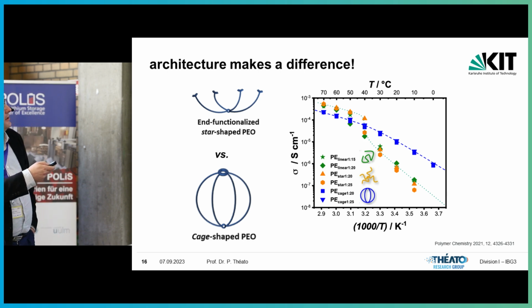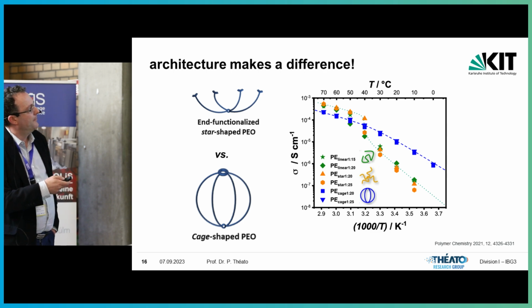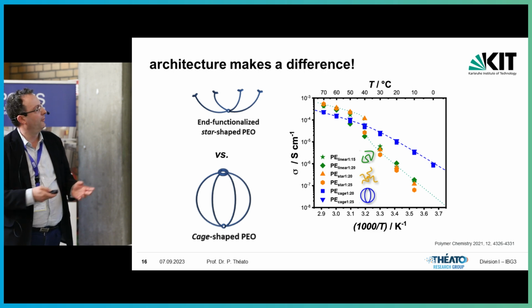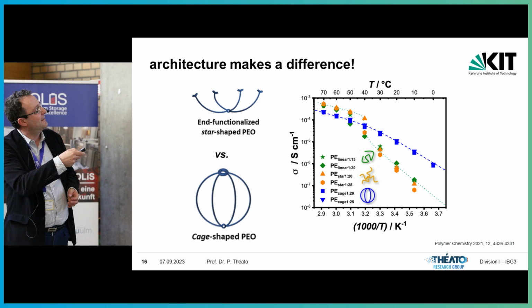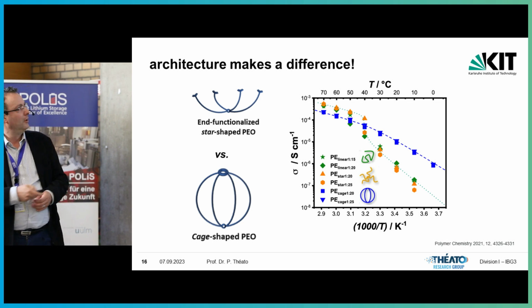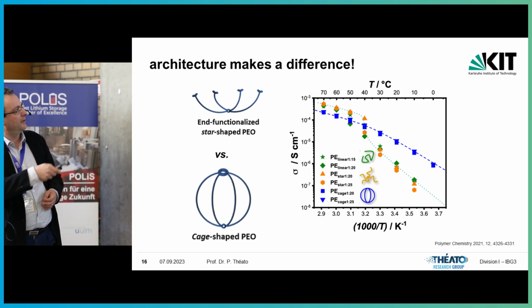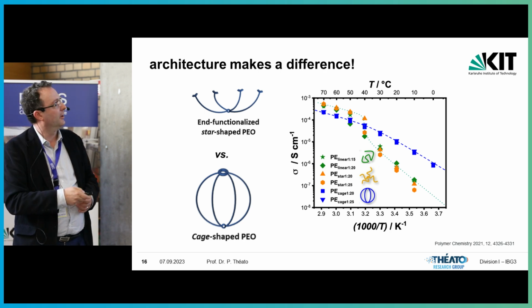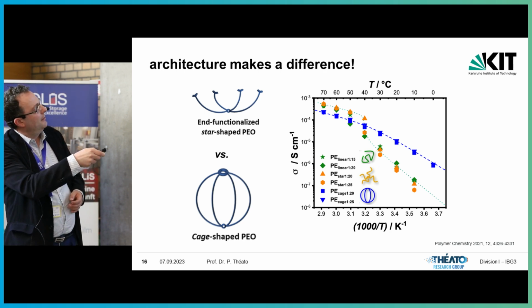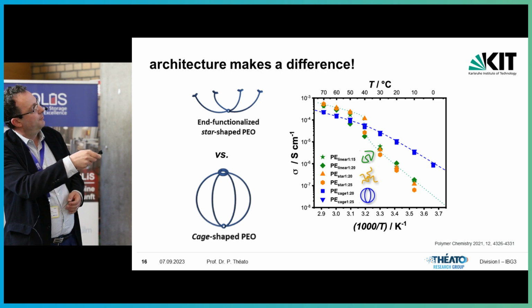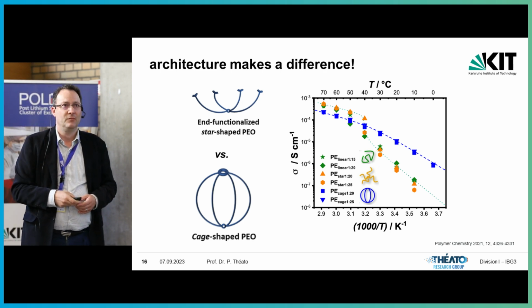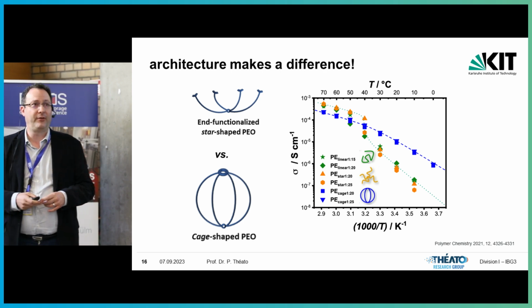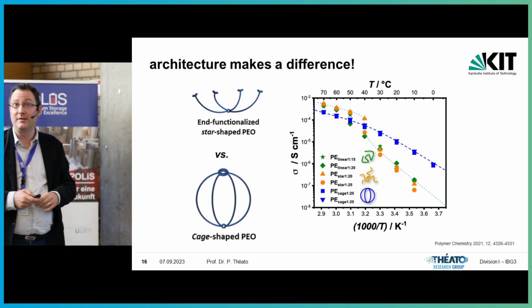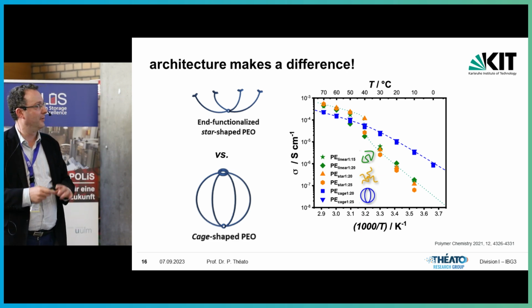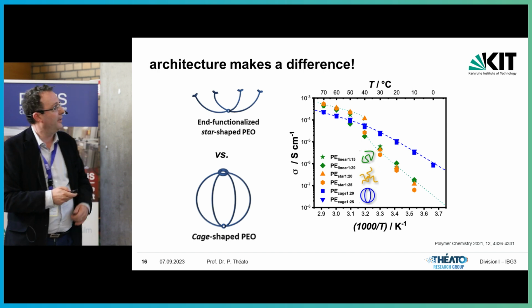So what you see here is the conductivity data of linear PEO in green. In orange, the precursor star, which has exactly the same chain lengths, molar mass relatively to the cage system, okay? So the star and the linear system in orange and in green are pretty much in line. So in contrast to Laurent's setup, here we do not necessarily see the difference between the star and the linear system. And I'm wondering why this is the case.